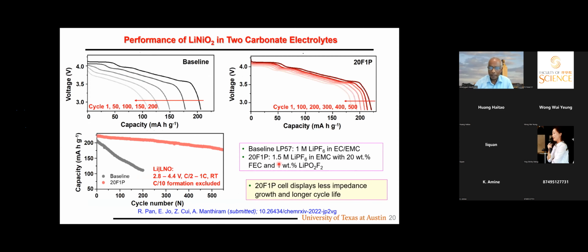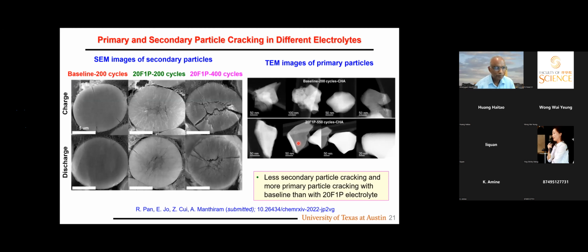This is another electrolyte. This is completely baseline, and another carbonate electrolyte. In the carbonate 20 F1P, it has 20 wt% FEC and 1 wt% LiPO2F2 compared to the other electrolytes. So we are comparing here. If you do that, again, there is a big difference in the cyclability. The capacity is falling off here, but the stabilized electrolyte has much better cyclability in both of these two plots. So why is it happening?